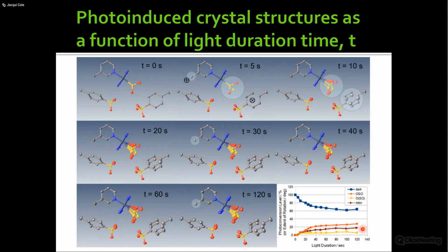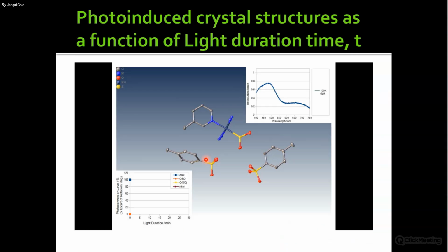So if you lose 20% of the dark state, you gain essentially 20% of the light-induced states in total, which seem to be split in this case between 2 different photoisomers, the side-bound and the oxygen-bound photoisomer. And the purple color with the triangles is the arene ring, what we call the rotor. That's growing in its population to help alleviate the strain caused particularly by the oxygen-bound sulfur in this formation. So that's starting to show you the order of events, in terms of a mechanism.